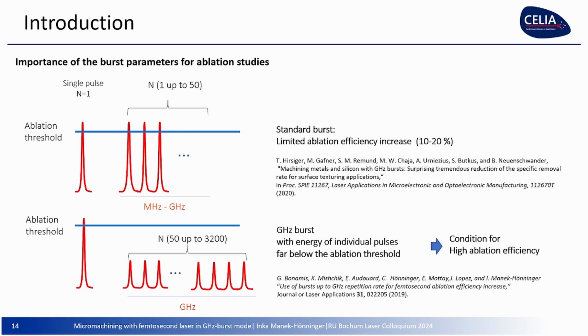Why? Because the first pulse ablates the matter, and then the second pulse is shielded by the ablated matter that comes from the opposite direction. And this was this paradox of even and odd pulses, and you saw sometimes it's better and sometimes it's less good. It was really odd numbers that gave better ablation efficiency than even numbers in this regime.